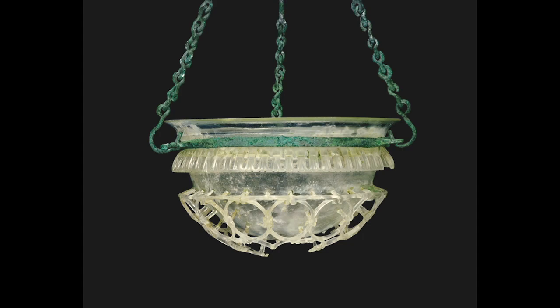Just as there are two kinds of glass, there are two ways to shape a piece of glass. Cold working is certainly the oldest way. This is our cage cup from the 4th century — probably made by blowing a very thick-walled blank, then passed to lapidary workers who carved it from the outside inward, ultimately leaving a thin-walled cup about 2.5 millimeters thick. Above and around the cup is suspended a decorative cage, supported by little struts. These are phenomenally fragile — the technology of cold working used here has, in my opinion, not been exceeded.